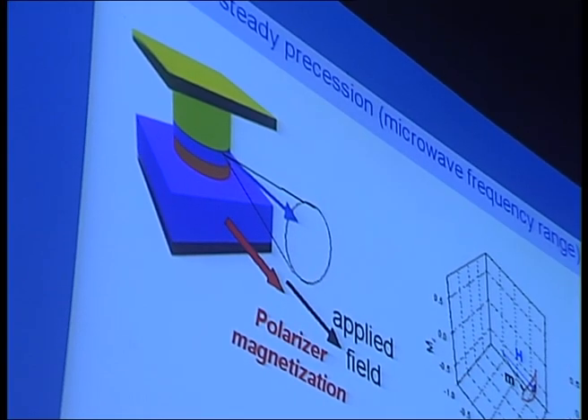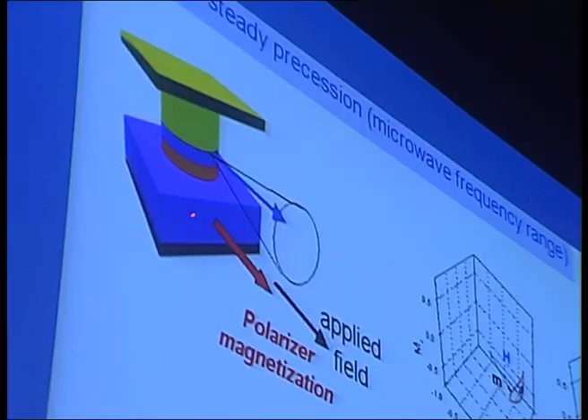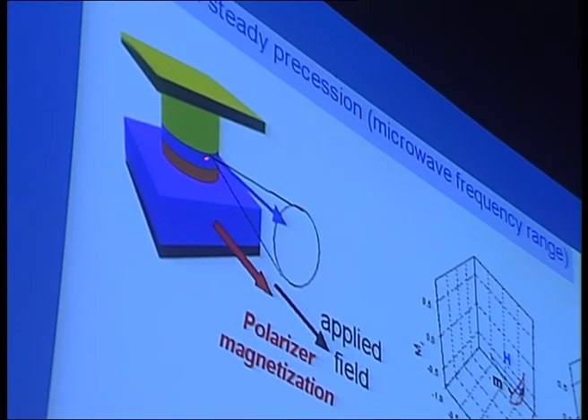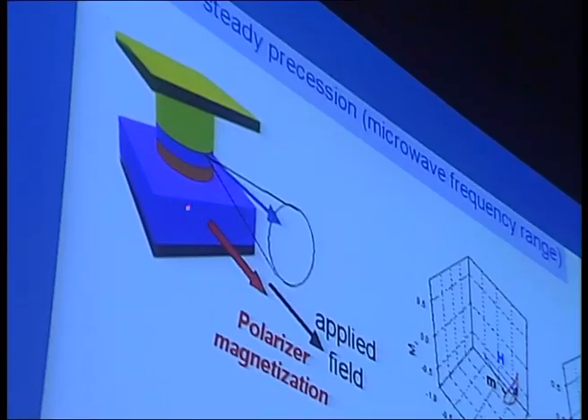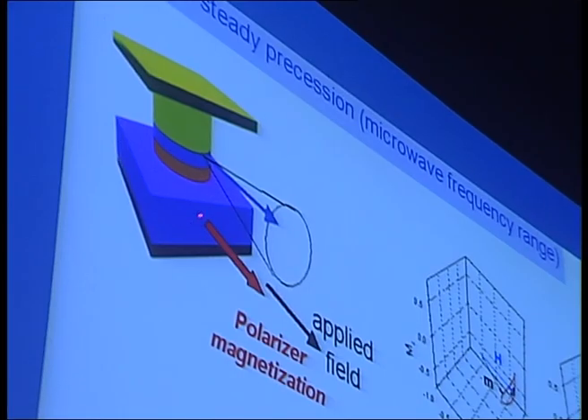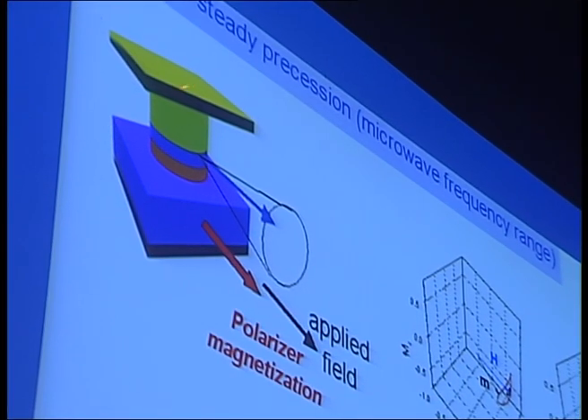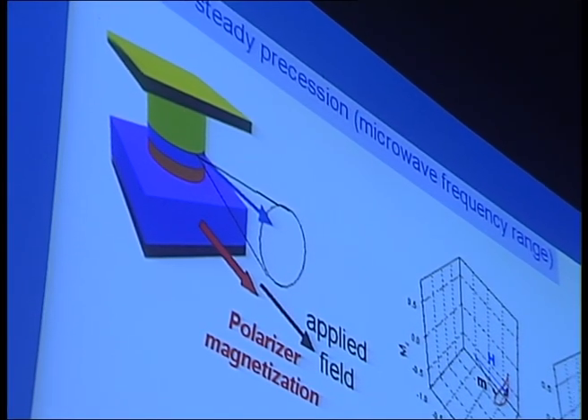During this precession, there is, of course, a periodic variation of the angle between the magnetization of the polarizer, the layer preparing the spin polarized current, and the magnetization of the free layer. And so, due to the GMR effect, there is a periodic variation of the resistance of the tri-layer, and so a periodic variation of the voltage between the top and the bottom of this structure.